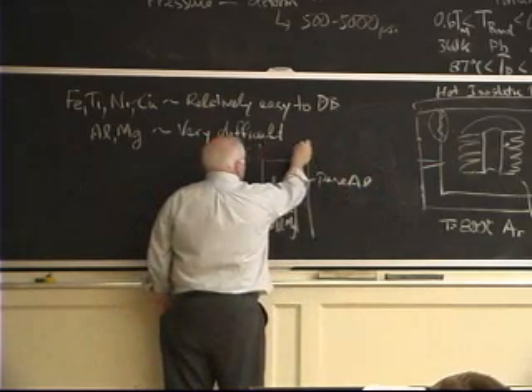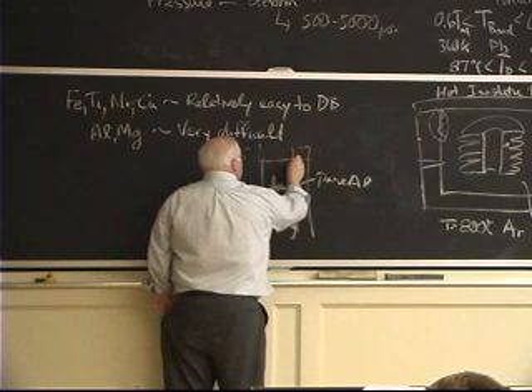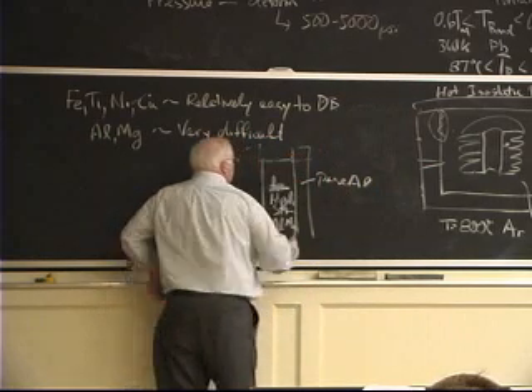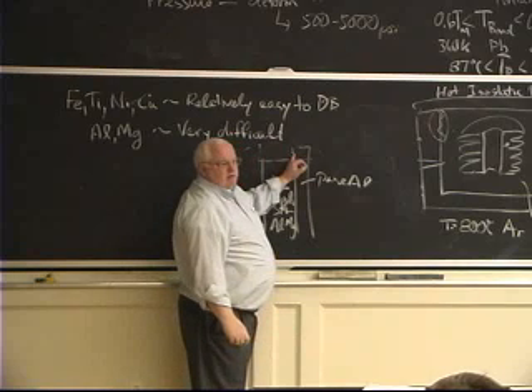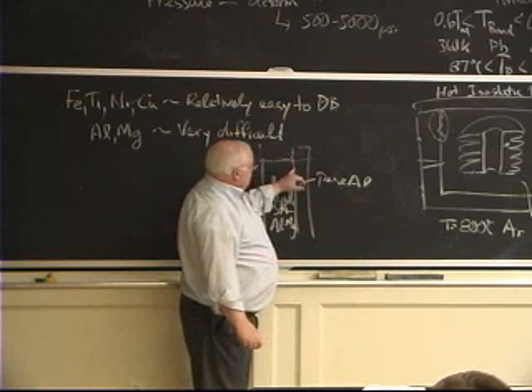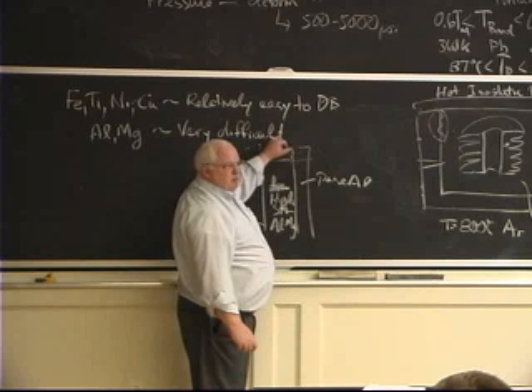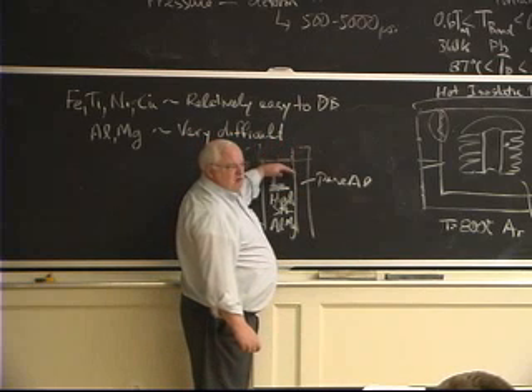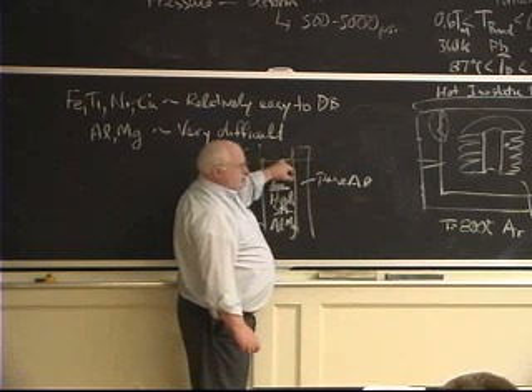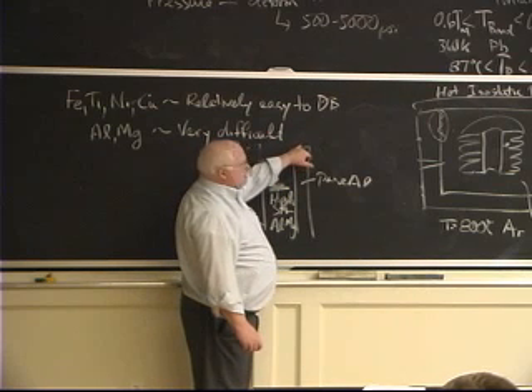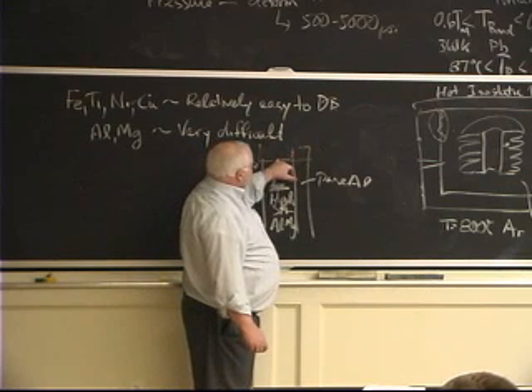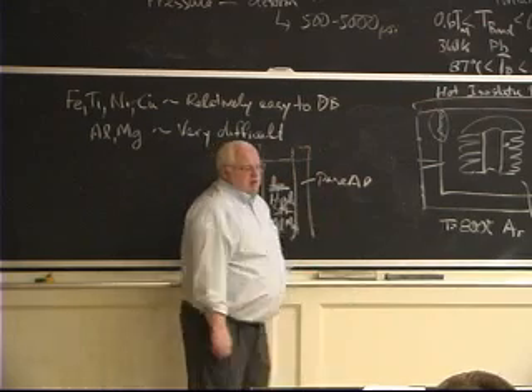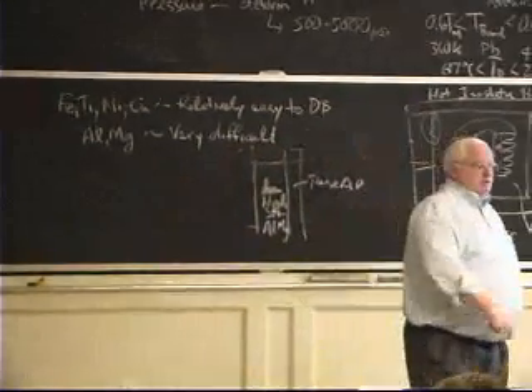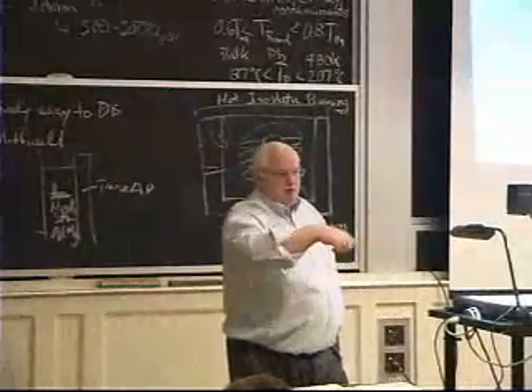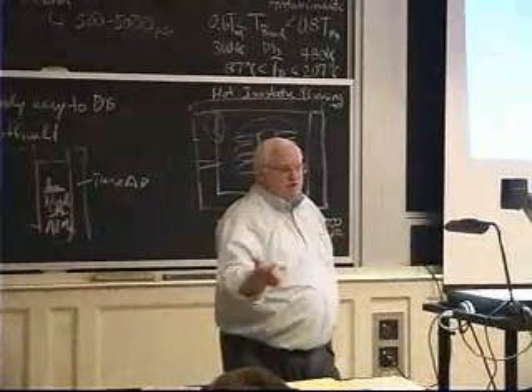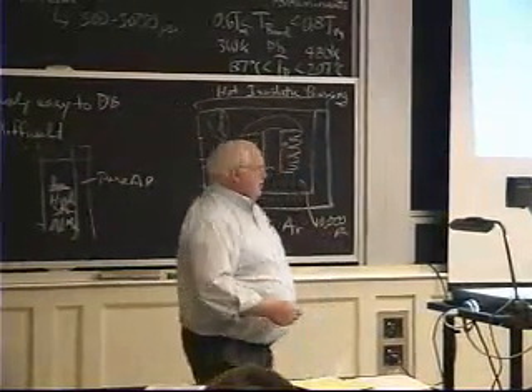But it turns out, by the way you design your furnace and everything up here, you actually, by radiant heating, melt a very, very thin layer of this. And so when this stuff comes up, you actually just kind of peel back that aluminum oxide skin. As this liquid floats up, the aluminum oxide floats off on this. And in fact, when this stuff is solidifying, you can take a steel rod and write MIT in the aluminum oxide skin. You can just write your name. I mean, I've done this when they're casting.